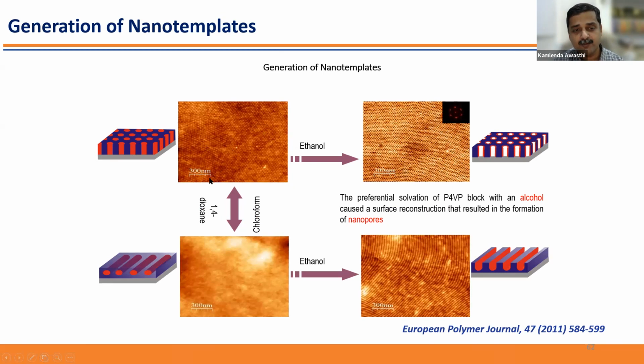By making, one most interesting part in this block polymer is that once we prepare the perpendicular structure, and later realize, okay, I don't need this, I want this, you just reverse it and put it in another solvent. So you can see this perpendicular morphology can be converted to this. And if you have this morphology, you can tune it like this. Once you remove the other component, the additive, then you cannot switch.